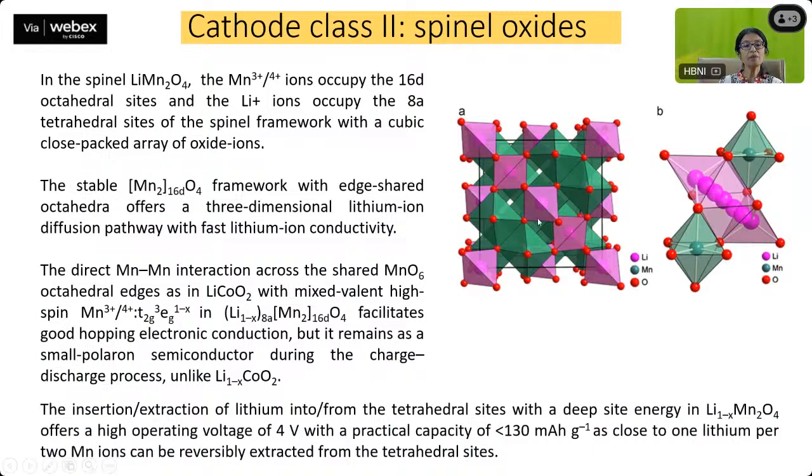So the stable Mn2O4 framework with edge-shared octahedra offers a 3-dimensional lithium ion diffusion pathway with very fast lithium ion conductivity. You have to remember, in the layered structure, what you had is a 2-dimensional pathway, whereas in the case of the spinels, what you're having is a 3-dimensional pathway.